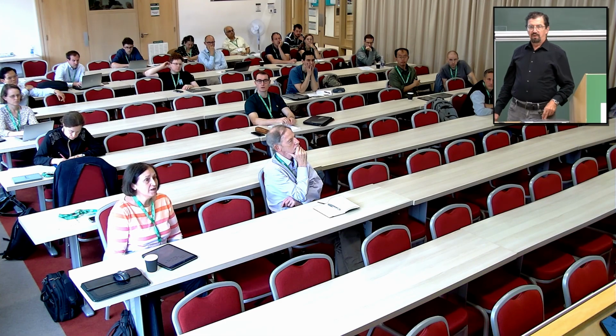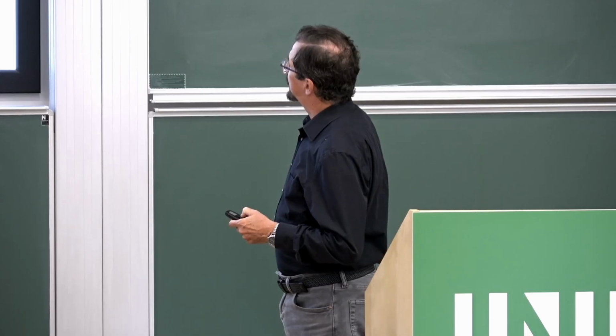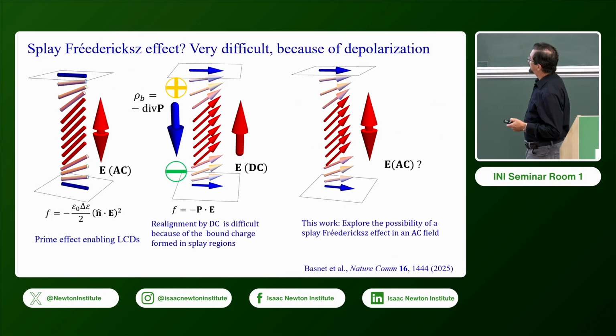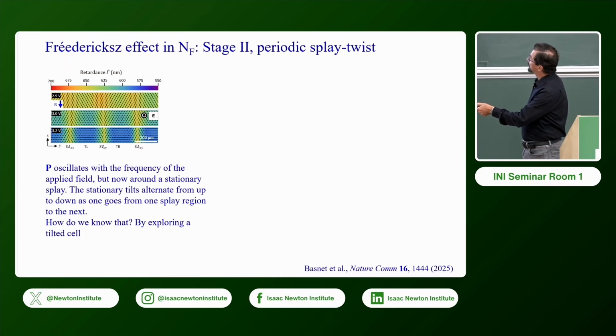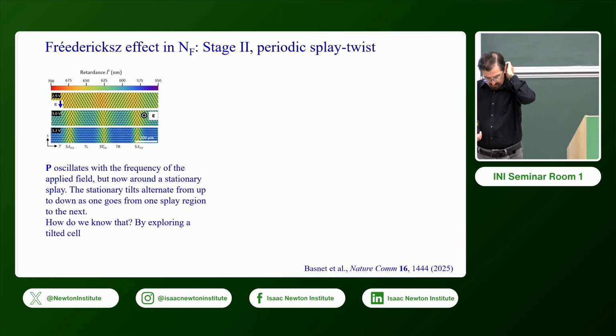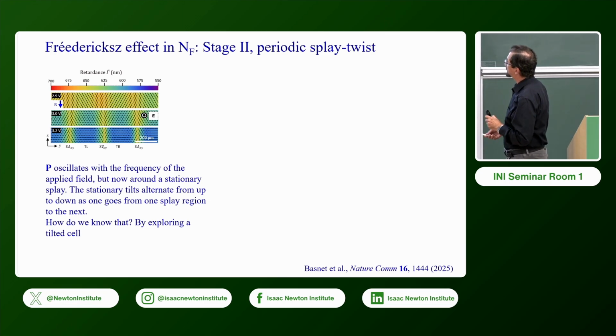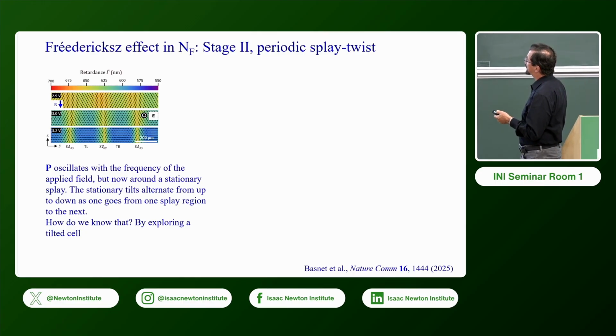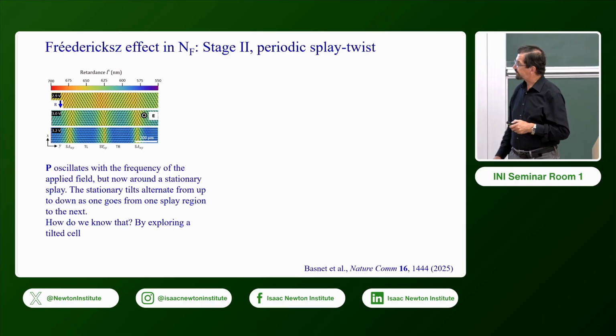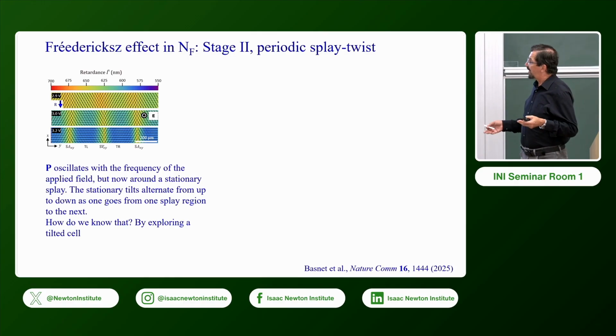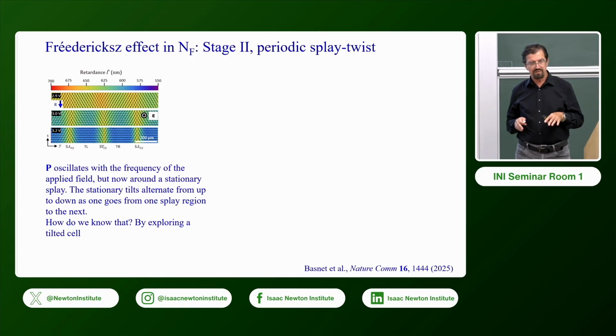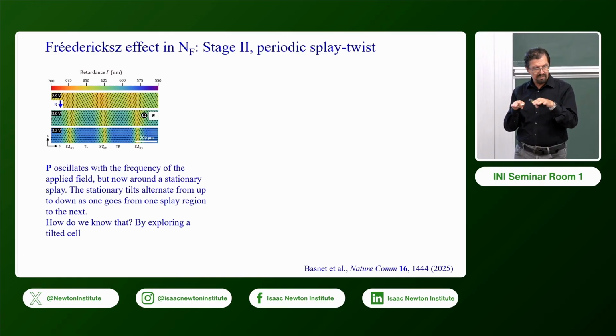Yes, please. It's very exciting. Do you have any significant issues with backflow? No backflow, because in the first two stages of this electrically induced realignment, when the system is homogeneously oscillating up and down, we don't see any hydrodynamics. We verified it with the tracers added to the material. And we also do not see any significant hydrodynamics in this regime because, again, we verified it. The reason for the absence of those hydrodynamic flows in these two regimes is that the oscillations are very weak. It's about half a degree, which is practically nothing.